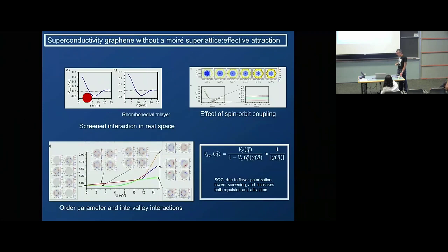That thing is easy to explain because you have this repulsive potential in Fourier space. You Fourier transform it, and because of the fact that as a function of Q it is more repulsive at large Q than at small q, you have in real space a potential which has attractive regions. And then when you apply the Zeeman spin-orbit coupling, you lose two valleys. So the screening is weaker, and then the repulsive potential is stronger. And when you Fourier transform it, the negative minima are also deeper. So that is a good justification for why you get a higher critical temperature when you lose valleys because of the Zeeman spin-orbit coupling.